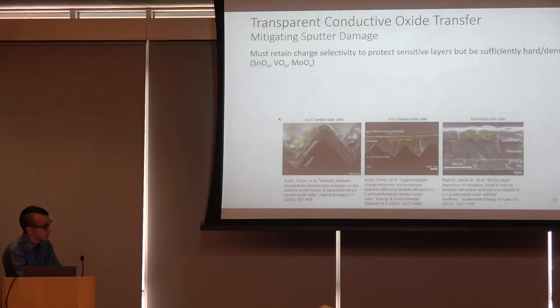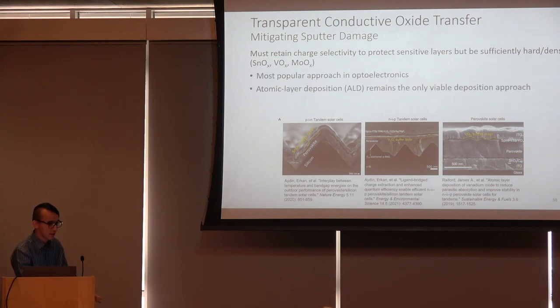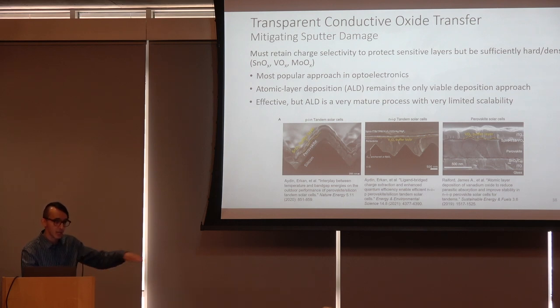In the tandem cell literature, the most typical approach to mitigating this damage is with the inclusion of a thin but dense hard metal oxide that is deposited by atomic layer deposition. As the name implies, you are depositing this one monolayer at a time, which makes it quite slow. There's some efforts in the literature to try and scale up this process sort of in line. And some of it is promising, but I think generally people still consider ALD to not be up to snuff for high throughput inline manufacturing.